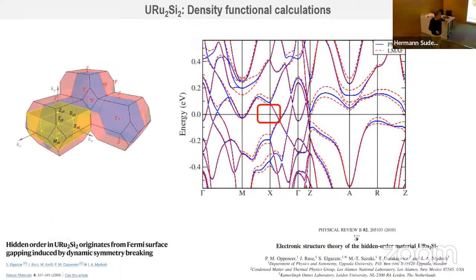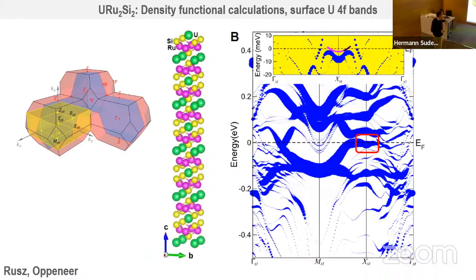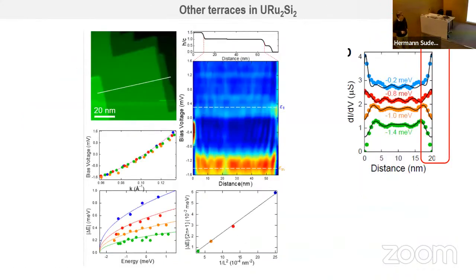So where do these states lie? There our friends from theory came up with this band structure. You see there are a lot of bands here, and there is one place here on which I would like to focus. I will come back to these two differences a little bit later. In this place, if you make the calculation with the slab and so on, you find that there are f electron states located here. And the f electron states have a dispersion which is similar to the one which we observe, despite some small shift here. So there are surface electrons there, and the surface electrons are kind of nice.